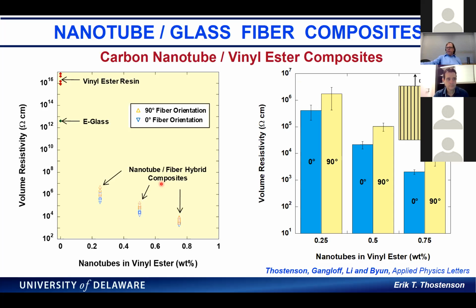In this Applied Physics Letters paper, I had a student, because the person would always ask me, does it vary, and does it depend on the orientation of the flow? Yes, of course. So I said, okay, we're going to make a panel. I had it at 90 degrees and 0 degrees, and we did the infusion all at once. Then I had them section it and do electrical property measurements along the whole length. The electrical property measurements and the fiber orientation during infusion were all within scatter. There was no spatial or orientation variation.